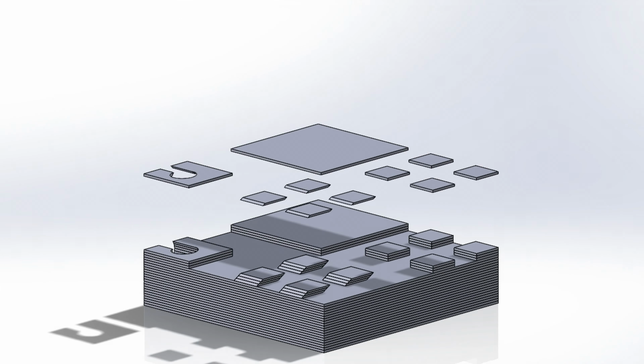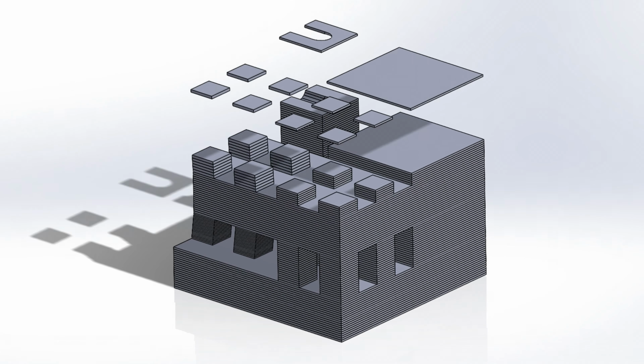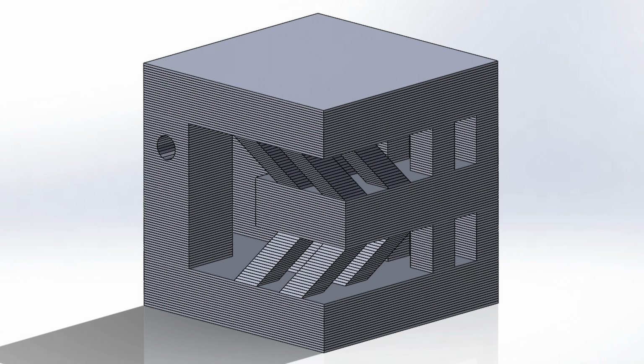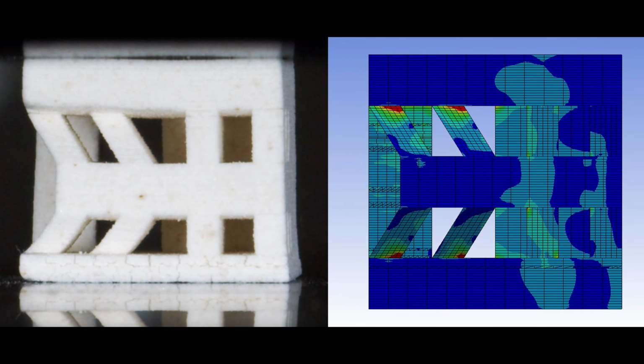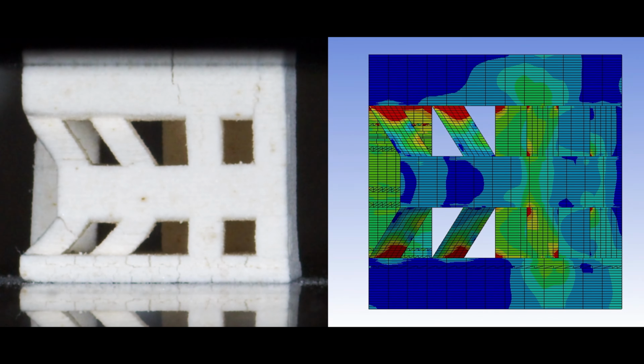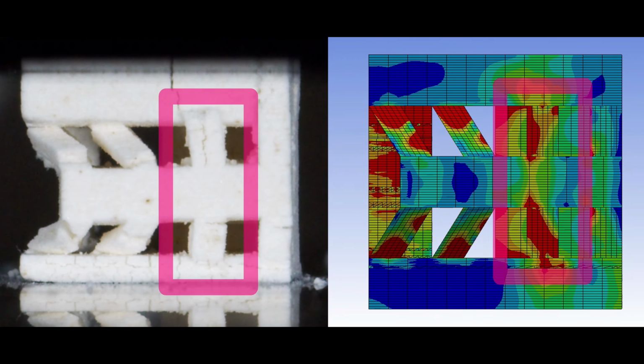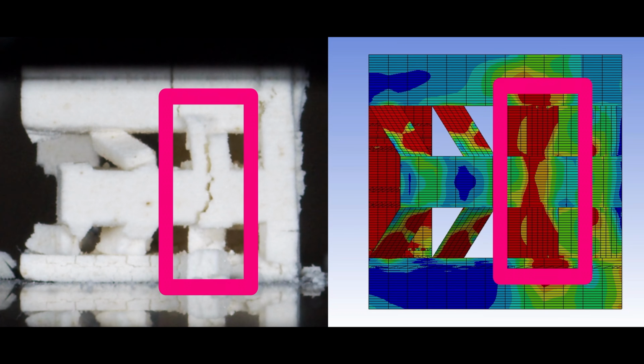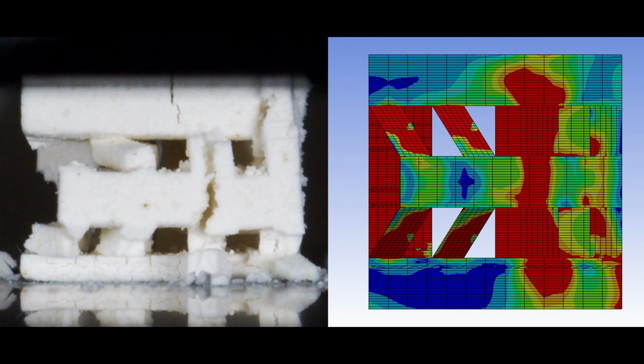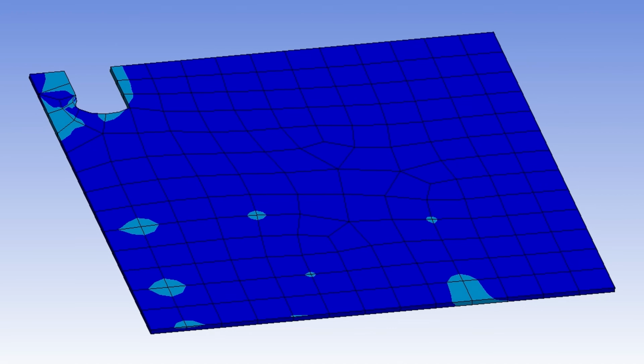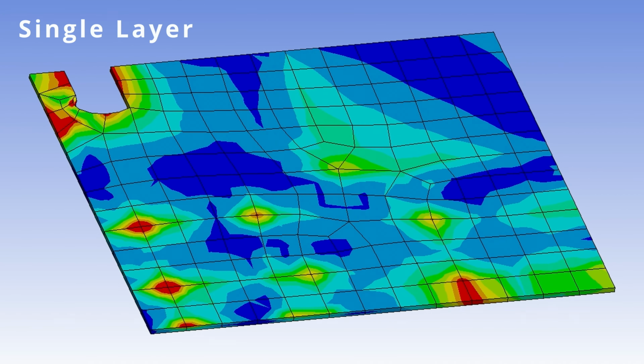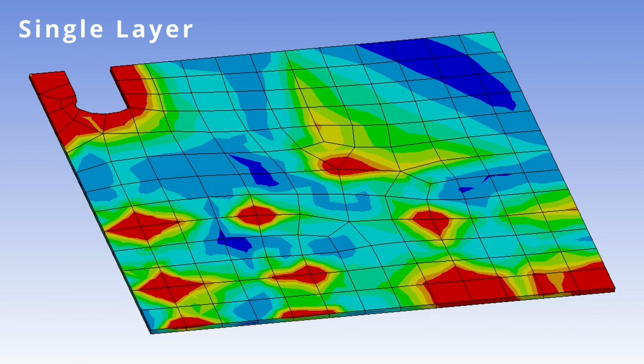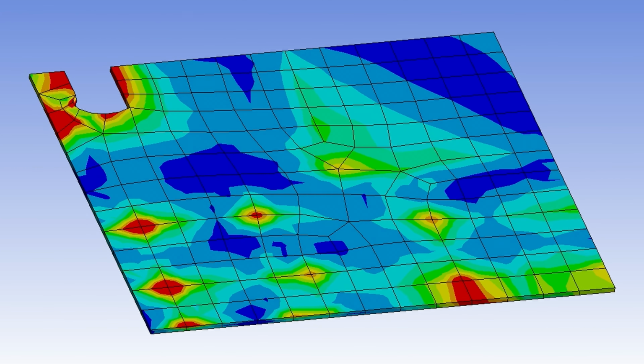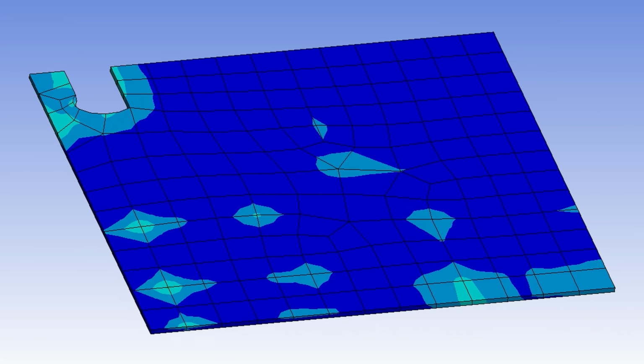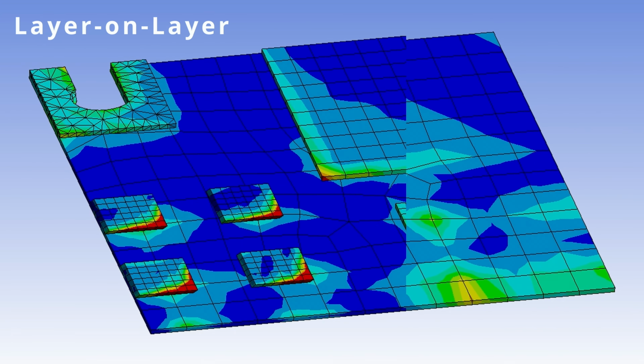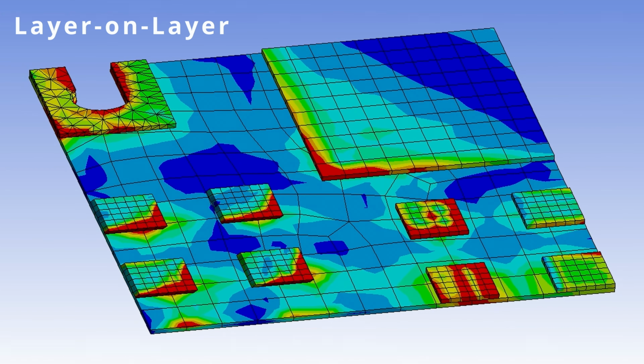We also created a 3D model of the complex cube calibration print layer by layer. This was really cool because it allowed us to create simulations based on the material. These simulations perfectly matched the experimental compression testing. What's cool about the simulations is that you can actually see what's happening in each individual layer. You could even see what's happening between 2 layers or 3 layers or whatever you want to see. This is valuable information when designing parts and structures this way for the moon.